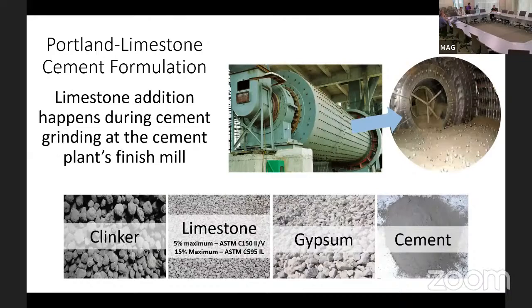So the Portland limestone cement formulation: that top green big barrel is what you call a finish mill, a finished ball mill at a cement plant. And to the right is a look inside that finished ball mill. Basically, a ball mill is just a high horsepower engine that turns, and these steel balls cascade. They're charged with different size balls, but these balls will pulverize the clinker, limestone, and gypsum to give you what you're familiar with, which is a finely ground cement.